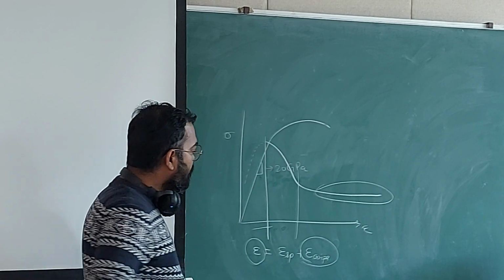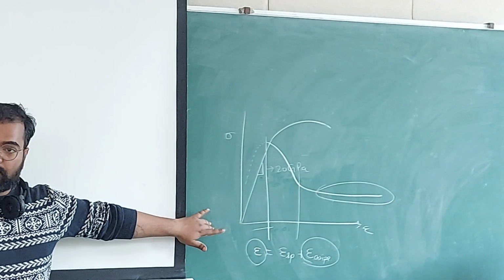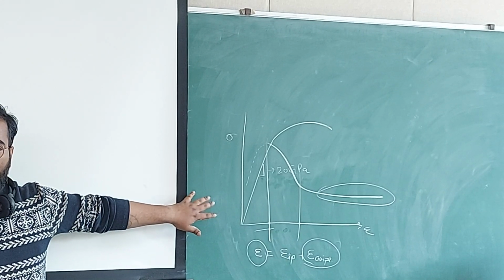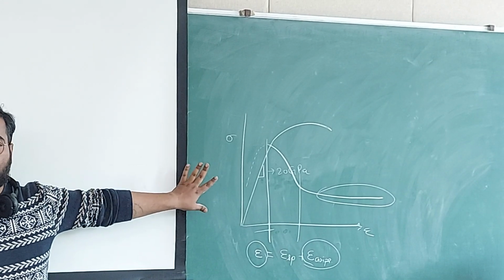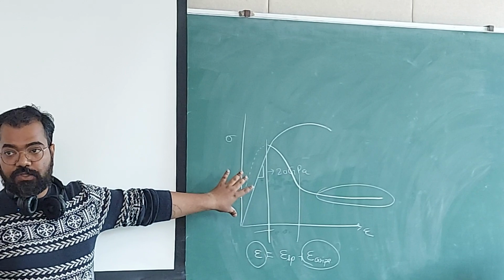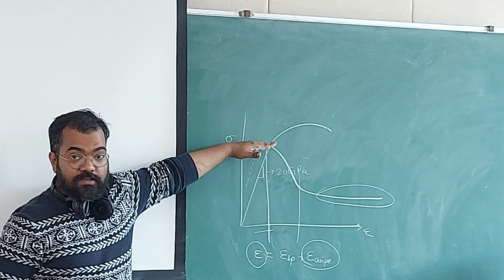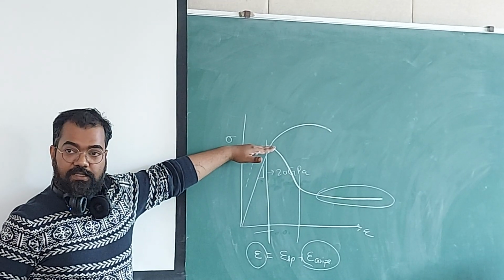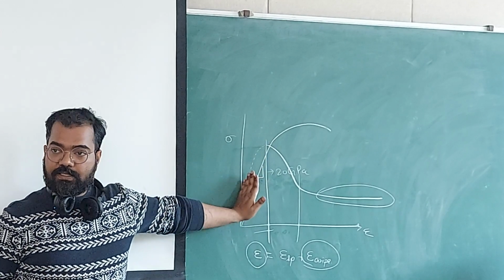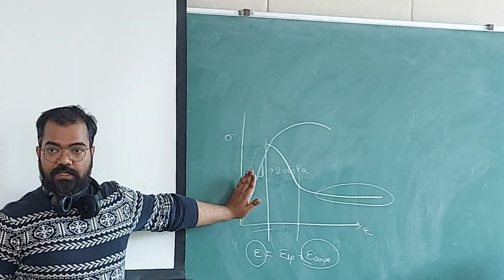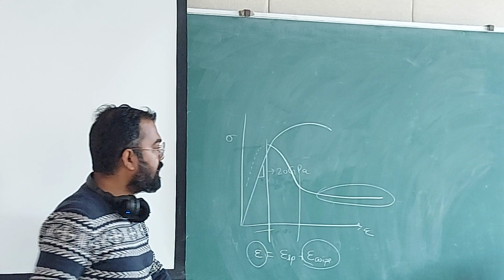Okay, and last remark is, if you go in plane stress condition, it increases, but there is a region beyond which, if you decrease the thickness further, people have different opinions and experimental values for this region. Some people find a constant value where it doesn't change. Some people find a decreasing value of fracture toughness, and those things are not known.